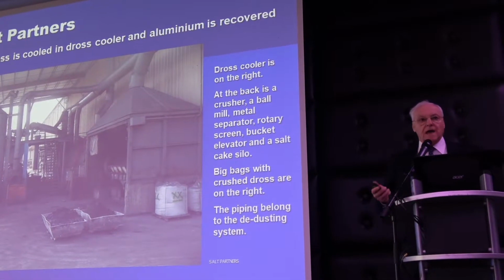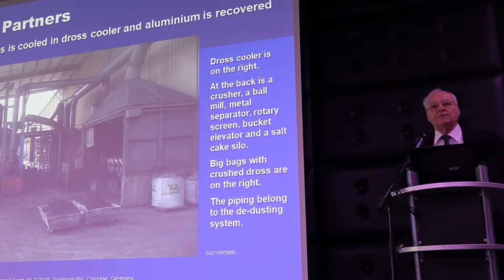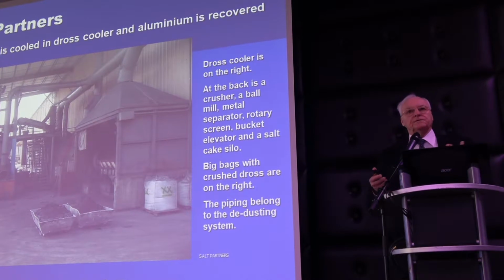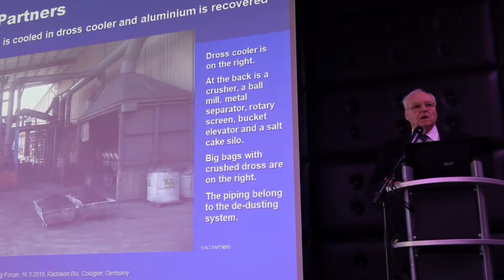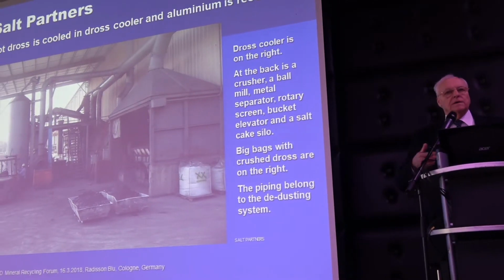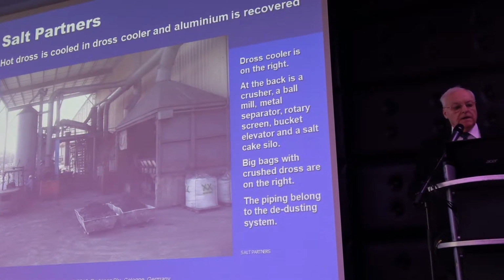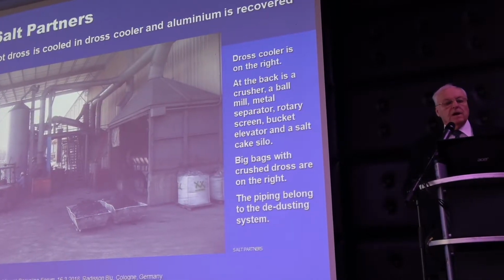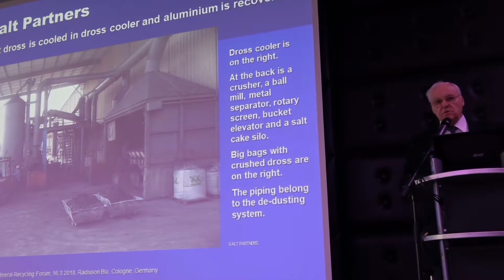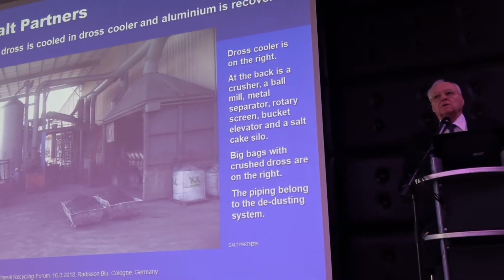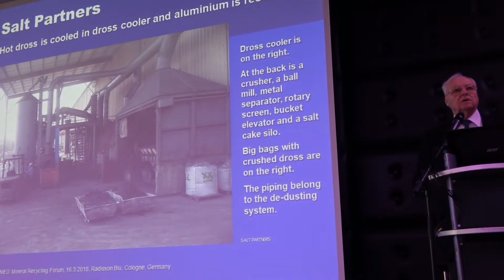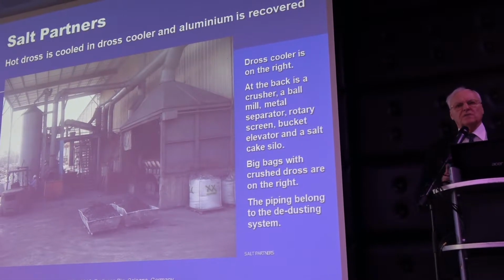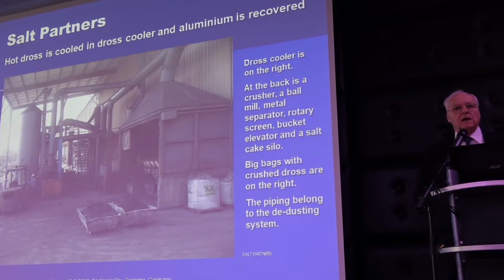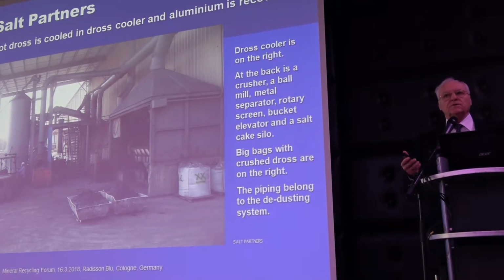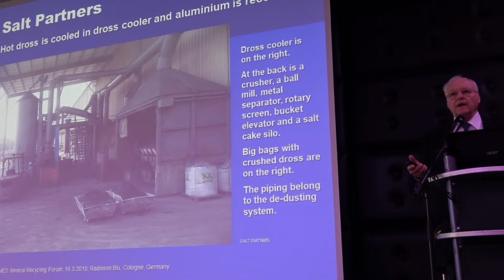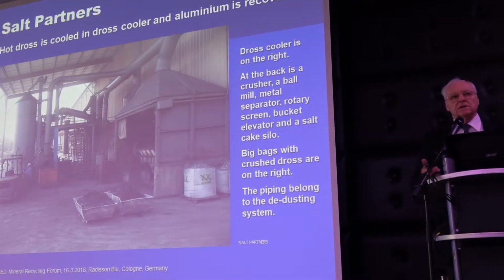Now the dross is a slag. It consists of about half salts and half aluminium oxides and other ashes, remainder of the beer and Coca-Cola that was still in the cans. Now, the very unpleasant thing about this dross is that when it gets wet, it begins to smell terribly. Not only ammonia, but all kinds of other very unpleasant smells. So to dispose of it is difficult. It has to be disposed of dry, and it's an expensive story.